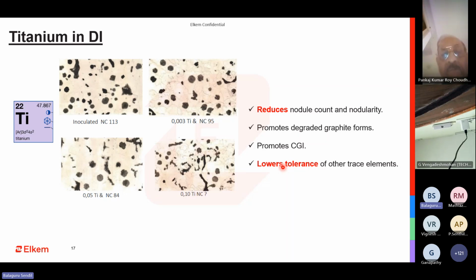So that is why it is more dangerous in ductile iron, and why we need to control titanium as low as possible. So this condition of 0.003 titanium, which gives me a 95 nodule count, can be brought down to 85, because my other trace elements are present in normal conditions that can be tolerated, but with titanium additions they cannot be tolerated, or the tolerance level drops. So this is the problem of titanium in ductile iron.